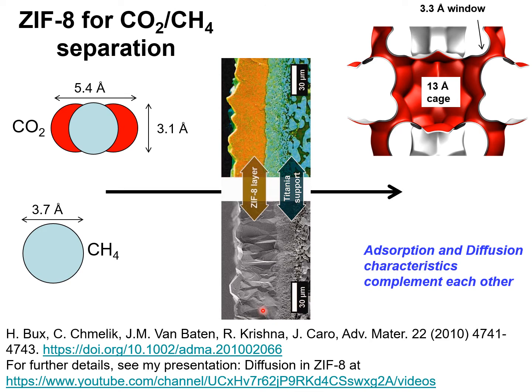Typically, the membrane would be constructed of thin layers of about 50 microns on a support, which is macroporous, in this case, say a titania support. And ZIF-8 is a good choice for separation of mixtures of, say, carbon dioxide/methane, carbon dioxide/hydrogen, methane/hydrogen.